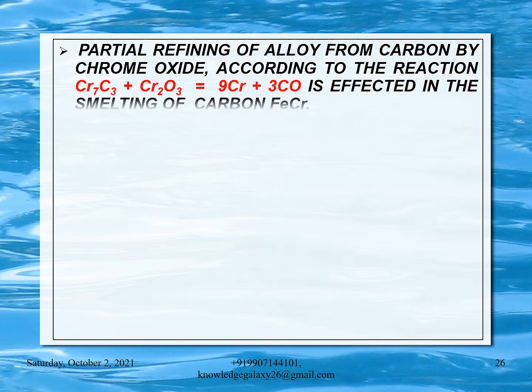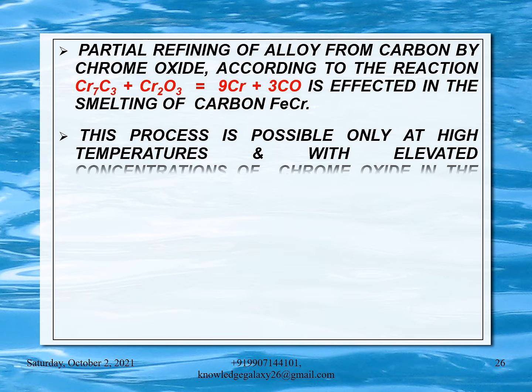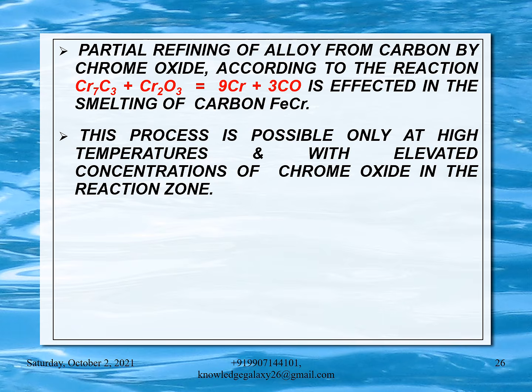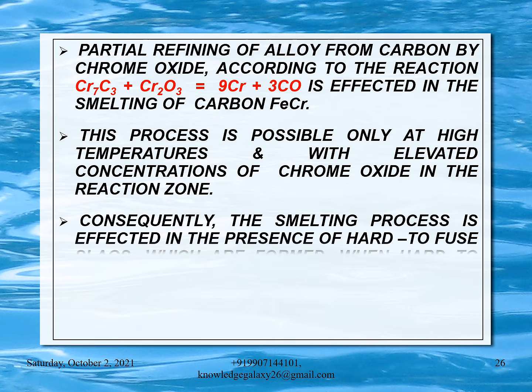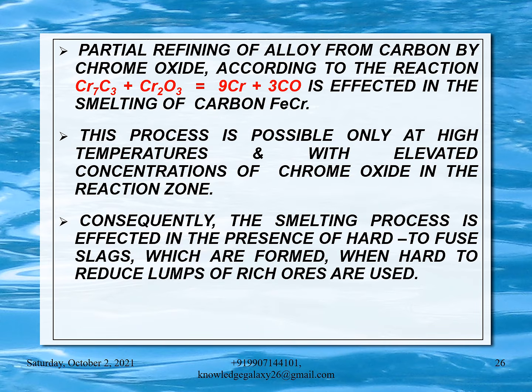Partial refining of alloy from carbon by chrome oxide according to the reaction Cr7C3 + Cr2O3 = 9Cr + 3CO is effected in the smelting of carbon ferrochrome. This process is possible only at high temperatures and with elevated concentrations of chrome oxide in the reaction zone. Consequently, the smelting process is effected in the presence of hard-to-fuse slags which are formed when hard-to-reduce lumps of rich ores are used.